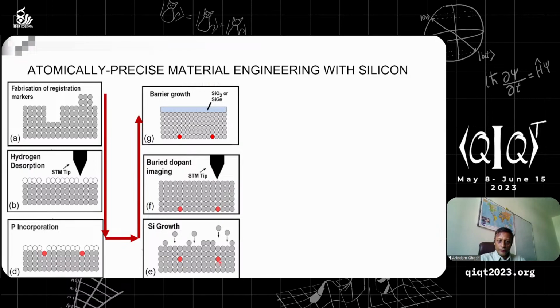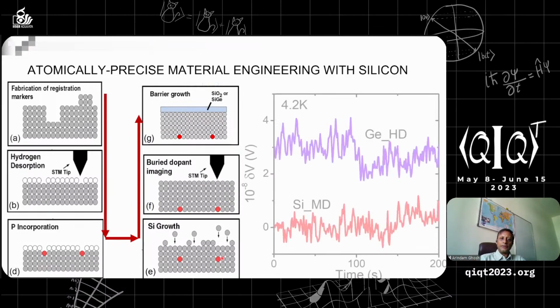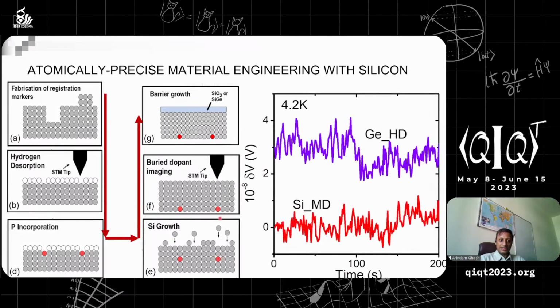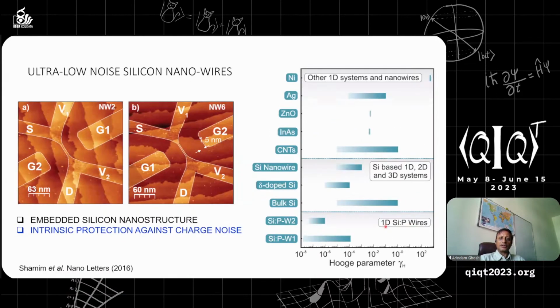So each of these two phosphorus atoms is like a qubit, and they interact with each other through exchange interaction. Okay, we measured electrical noise in such systems, and we found that these systems have the lowest noise in nature of all systems of this dimension. For example, if you make these phosphorus atoms along these lines over here, and you measure their noise properties, this axis is noise magnitude.